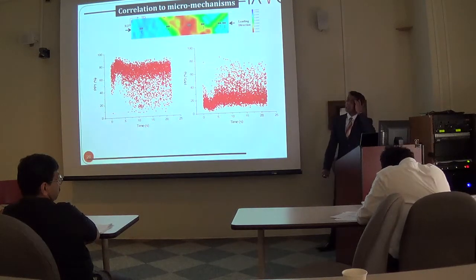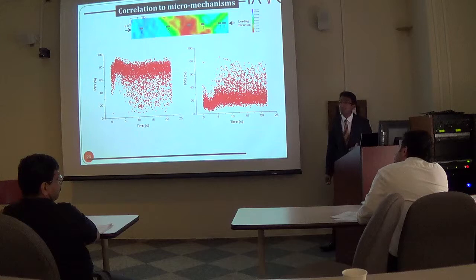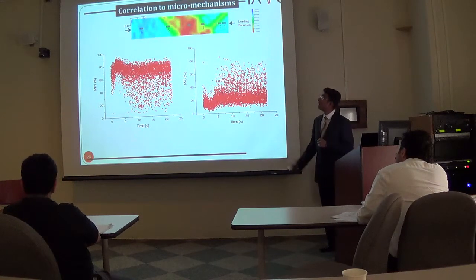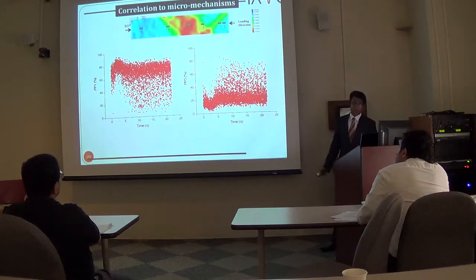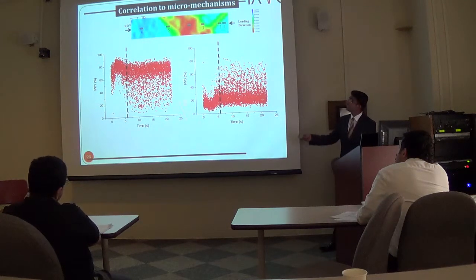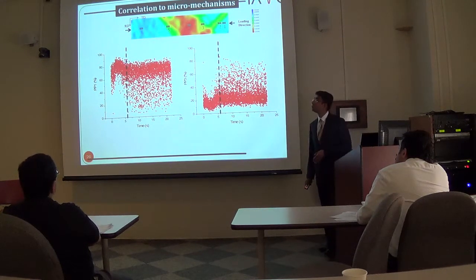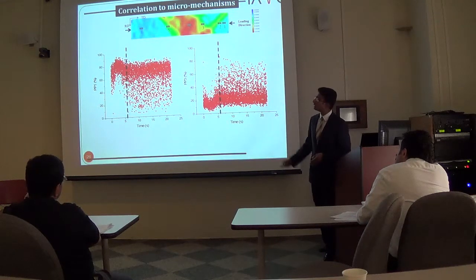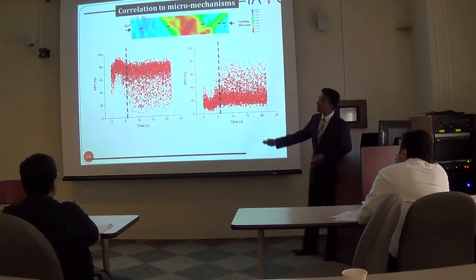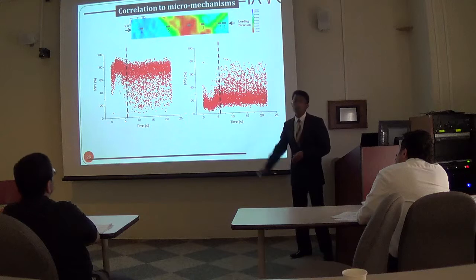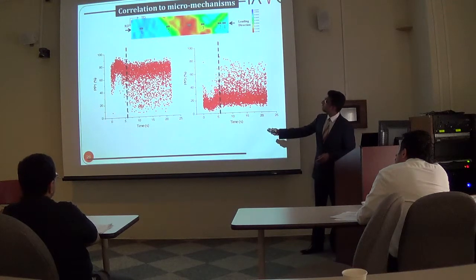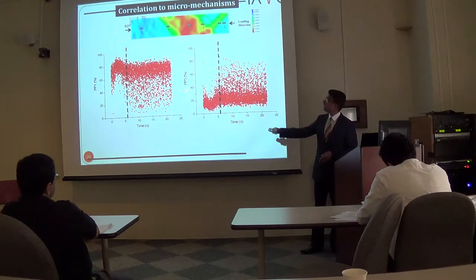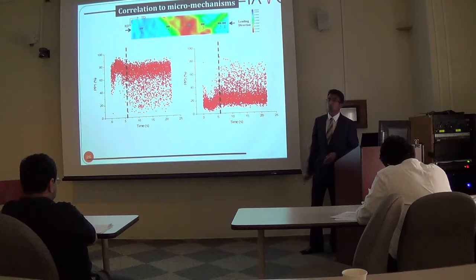Now, in order to see if the advanced frequency analysis can be utilized to track this evolution, partial power analysis of the waveforms was extracted and applied, and it can be clearly seen after the 6 seconds, where we noted the activation of localized strain bands, a shift from the higher values of partial power 1 to lower values of partial power 1, while partial power 3 is seen to increase from its initial lower value to a higher value.